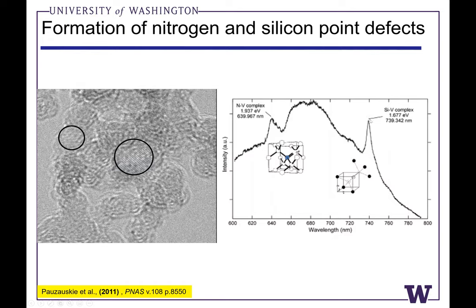And after looking into the literature, we were really excited and surprised to see that these well-defined peaks, this is about 640 nanometers, this is a peak at about 740 nanometers, both of these peaks correlate very closely to the negatively charged nitrogen vacancy center at about 640 or 638 nanometers, and also the negatively charged silicon split vacancy center at about 740 nanometers. And these have been well known for decades, thanks to research by De Beers and others to try to understand point defects in diamond.